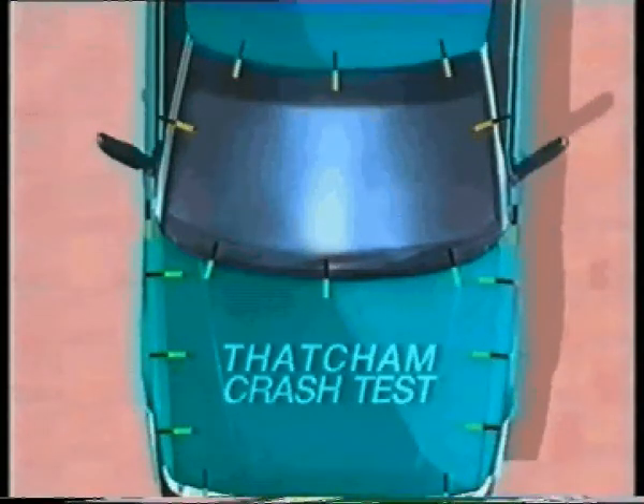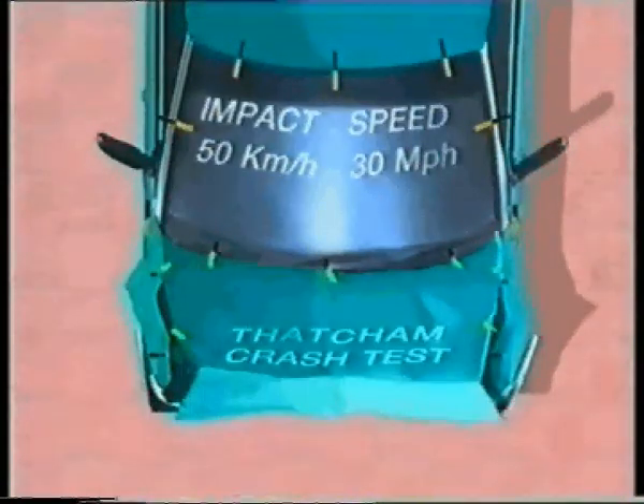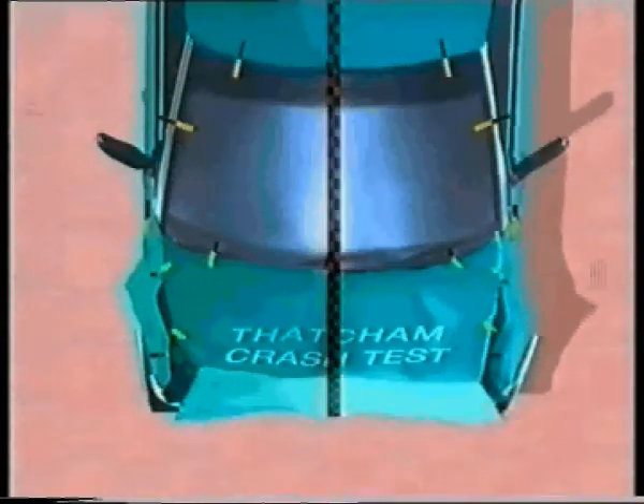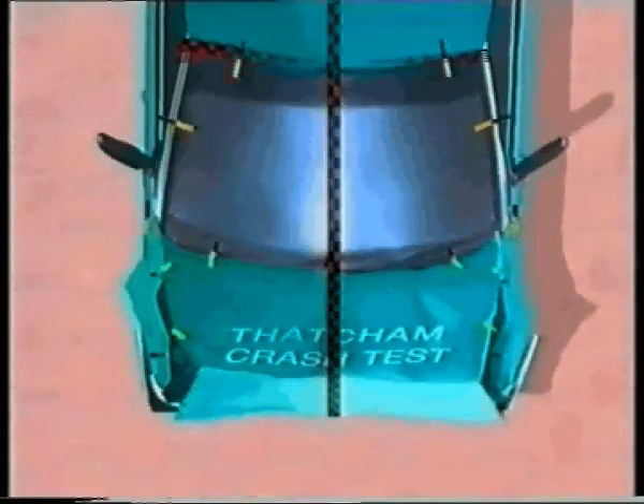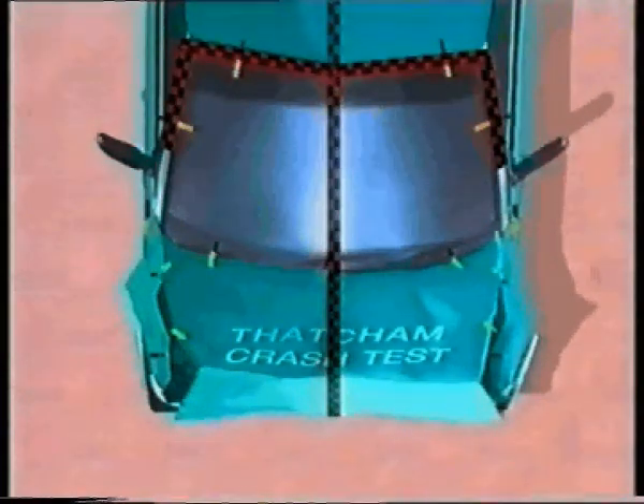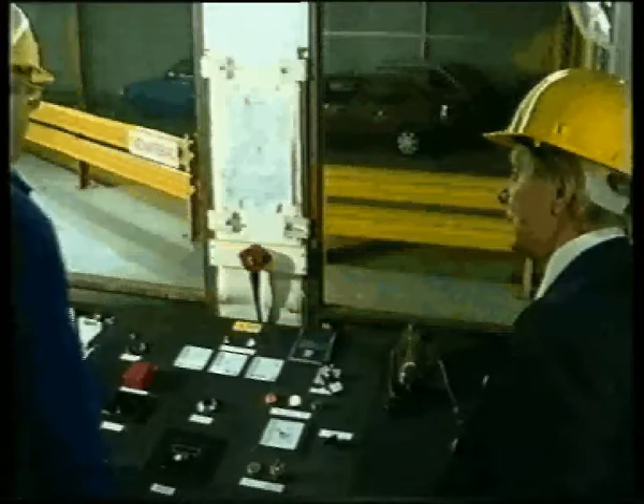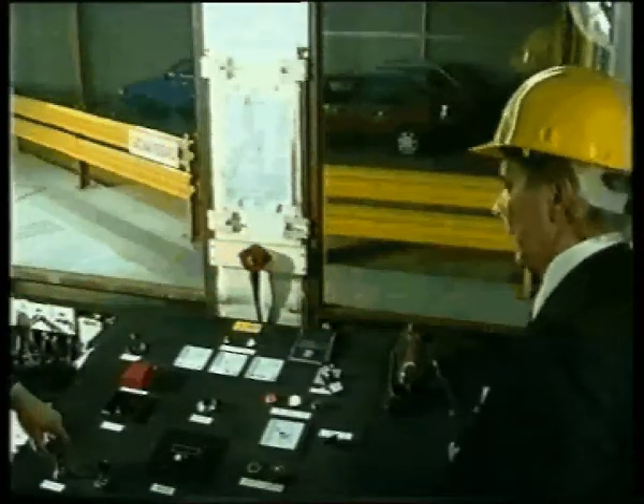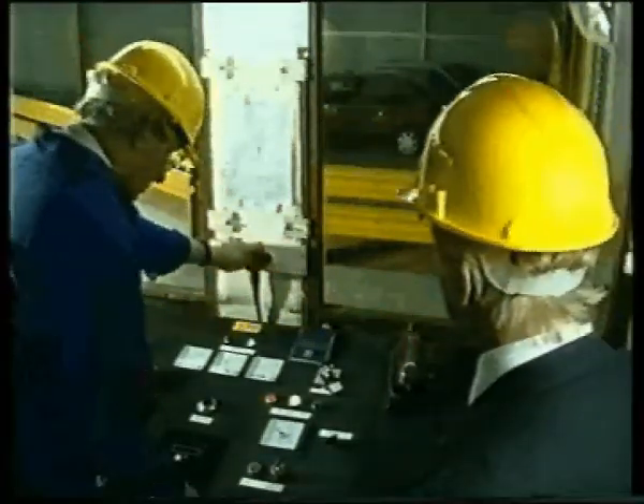The test conducted by Thatcham required the vehicle to be subjected to a full frontal impact into a static concrete block at 50 kilometers an hour. If the screen is then divided down the middle, the bond must have been maintained for at least half the way round the edge on each side in order to pass the test. The impact was set to occur 1 hour after fitting the screen, the worst possible situation to which the adhesive would ever be subjected in actual use.